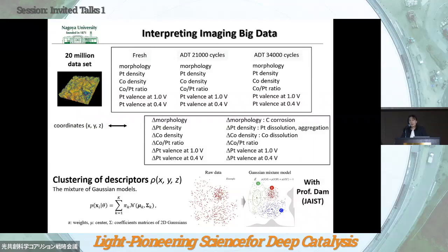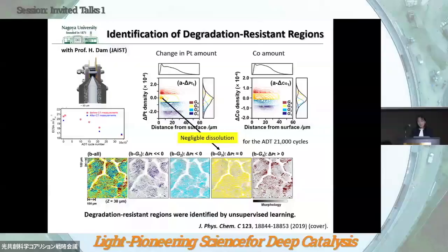Collaboration with a data scientist is quite important, and we started the clustering of these parameters obtained experimentally, and we analyzed the imaging big data by unsupervised learning for the degradation process of the platinum catalyst. Here, I would like to show you one example to identify degradation-resistant regions in a practical cell. We calculated quite many parameters, for example, the amount of the catalyst, some related to the dissolution or aggregation, the platinum density, cobalt density, and some of the geometric parameters inside the heterogeneous structure of cathode catalyst layers.